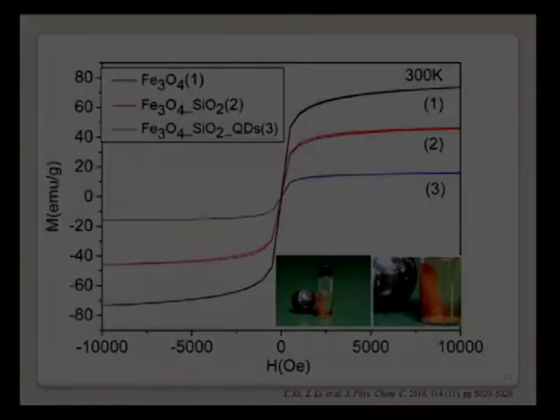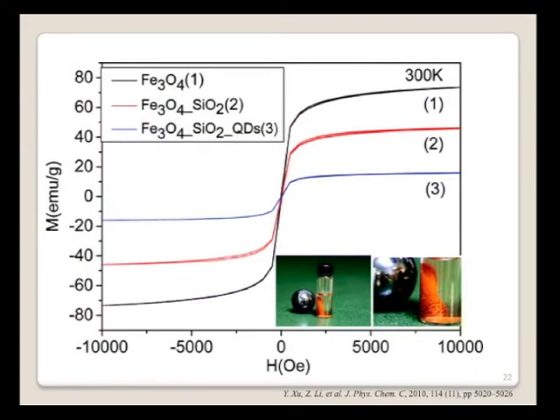Okay. How does this coating treatment affect the magnetic property? Is it still magnetic? We did magnetization for all these materials. The black curve is iron oxide. You see, it has a very strong magnetization value. After coating with silica, this magnetization drops. It makes sense because silica is a non-magnetic material that is screening the magnetic field. When joined with quantum dots, the magnetization value drops again, but it still has a lot.